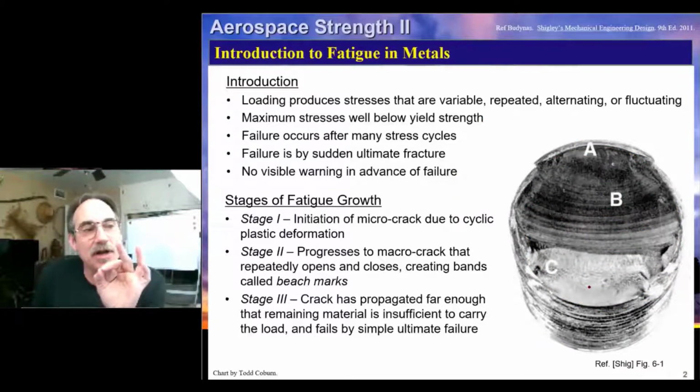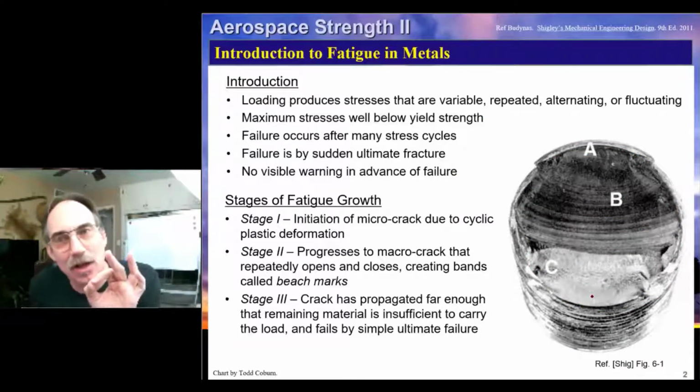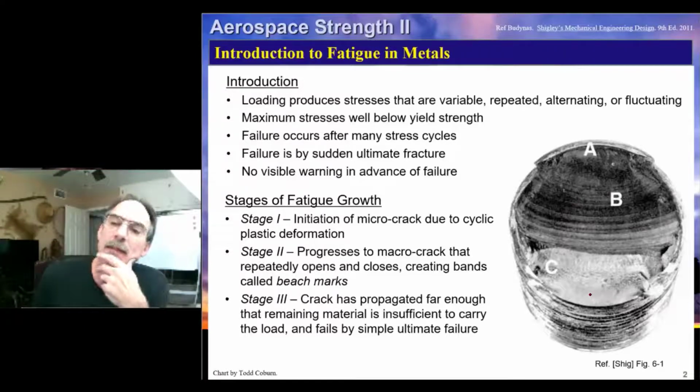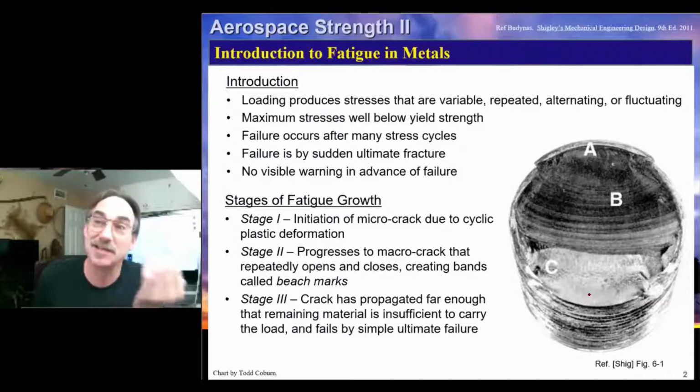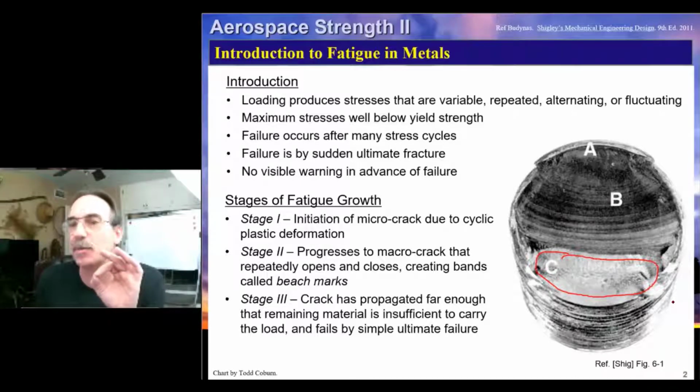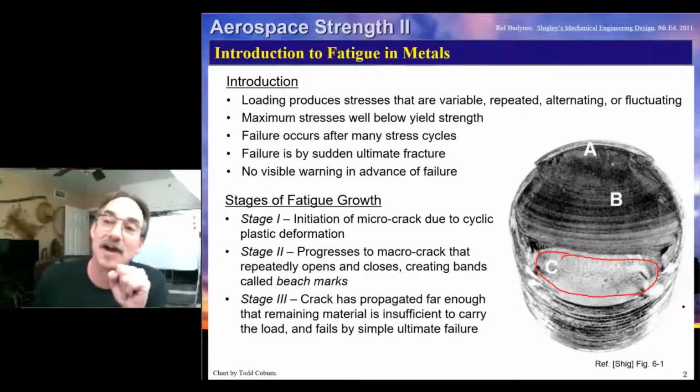If we look at this structure, do you think this was a high load or a low load that caused this fatigue problem? A low load. Why do you say that, John? Because you have a lot of beach marks, and if it was a high load, it might have failed sooner. Exactly. There are two things you can look for. A lot of beach marks means it was probably low load. And secondly, a small failure area. It only needed the part of the thing left to withstand the loading before fast fracture.